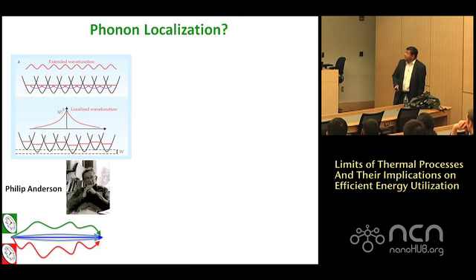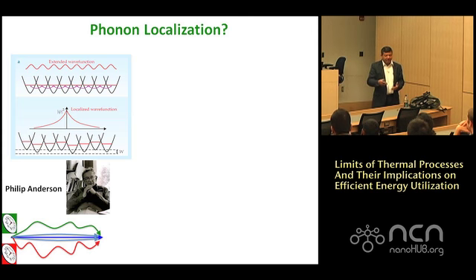And there's a famous paper by Phil Anderson in 1958 called Anderson Localization. And Anderson Localization says that if you get a metal, for example, and the metal is conducting, if you increase the degree of disorder in the metal, these electronic wave functions will scatter, but they will scatter in such a way that locally they will interfere destructively. And essentially the wave packet will not propagate. You will localize it, and you'll get evanescent waves. And thereby you can make the metal an insulator.